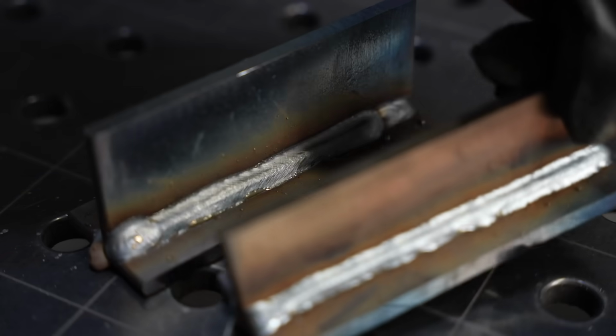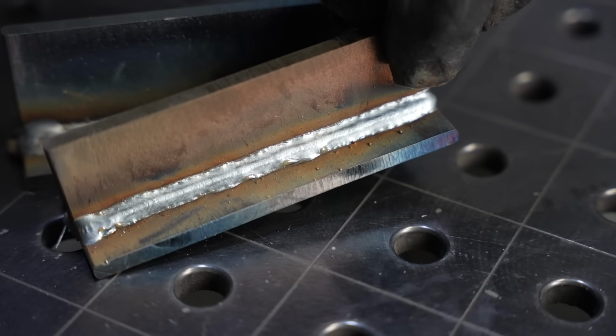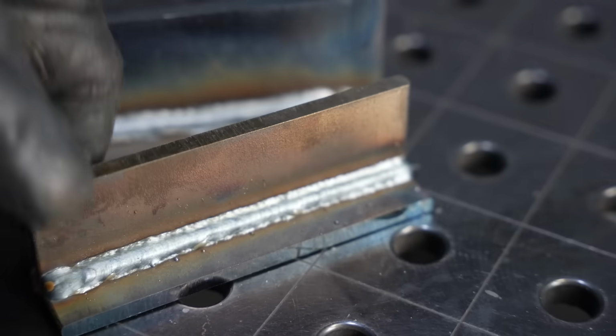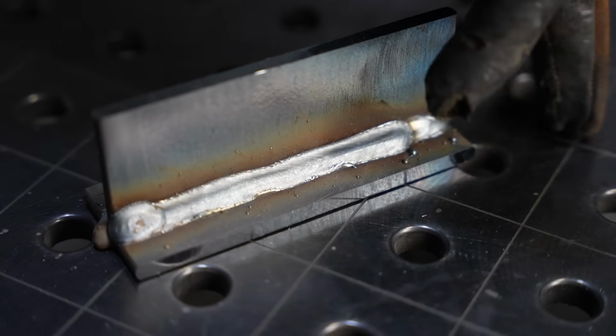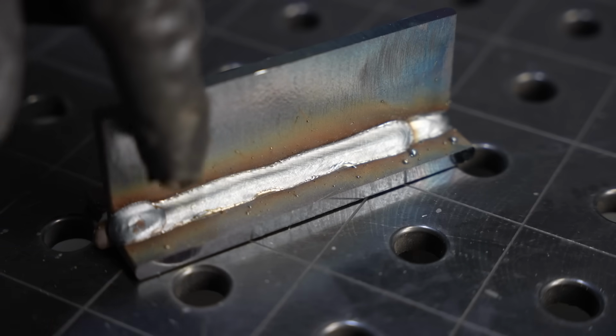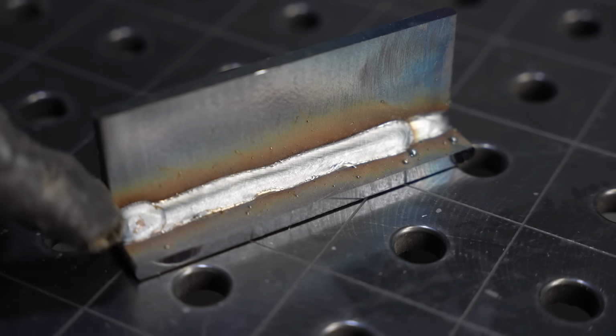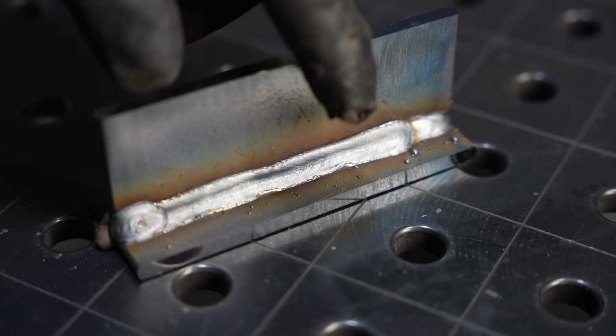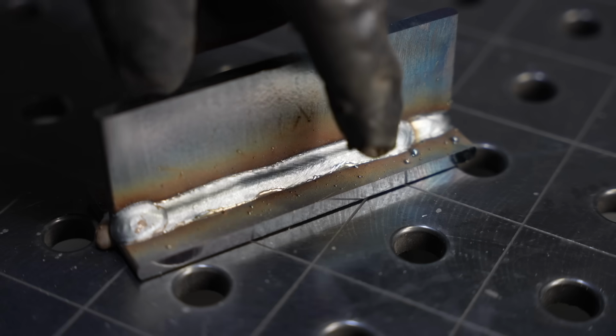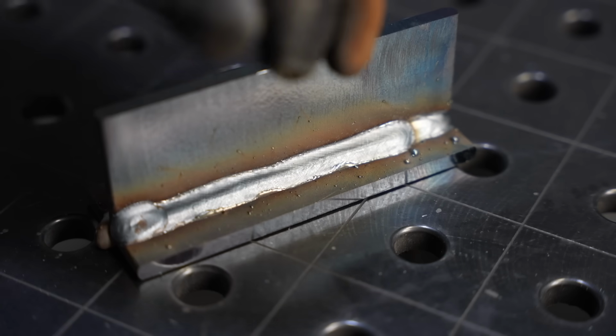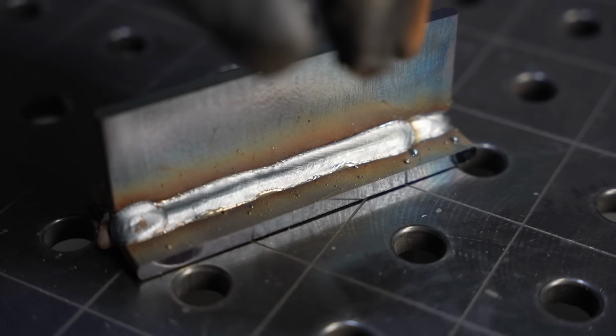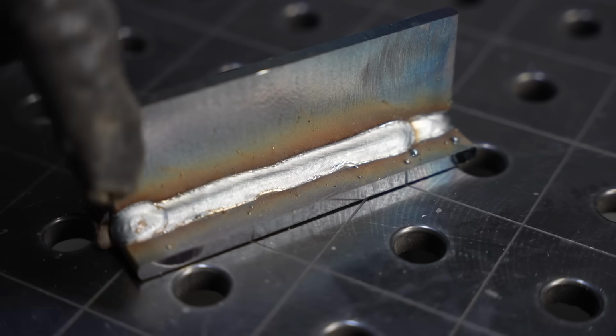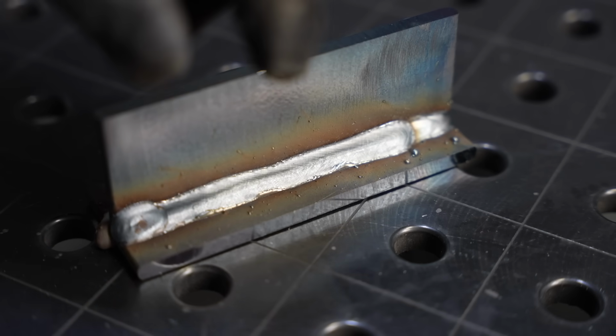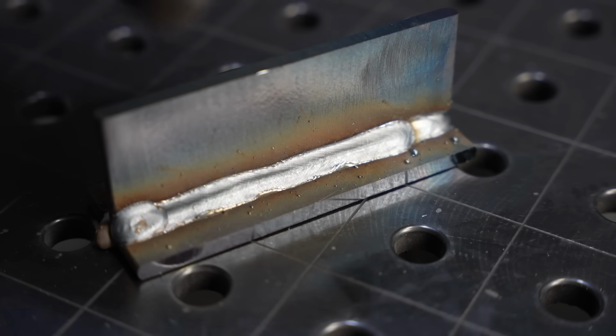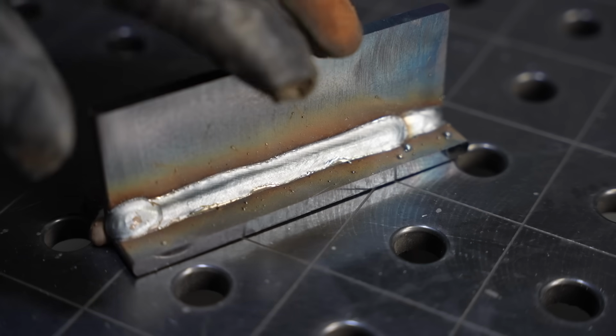So this was 030 on quarter inch. Not too bad, but definitely was at the top end of the wire. This right here is that 035, still pretty good. But when you start getting into the 045 right here, you ignore the start where I was still down in the settings, but right here, that is what I like to see in a weld, nice and smooth. Now, a lot of guys will run 030 wire and they'll run about the same settings at 200 inches per minute, like I was running on the 16 gauge, and do a whole bunch of loop-de-loops. And that's a whole art in and of itself. And I'm not saying that that can't be strong or that it doesn't look great, but for me, I have a lot of confidence in a weld like this. So I think that 045, those larger wires, if you have a machine that can push it, not all machines will, but if you do, then you get to quarter inch and above, really good pick.